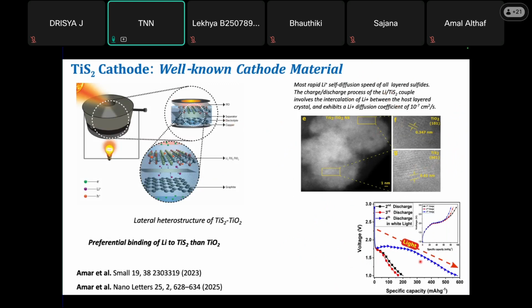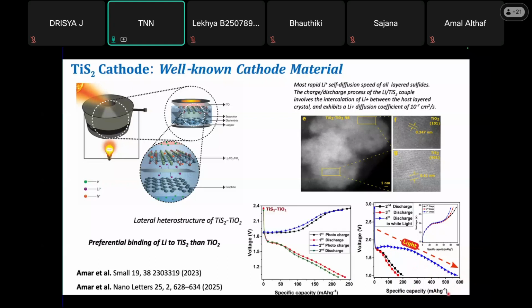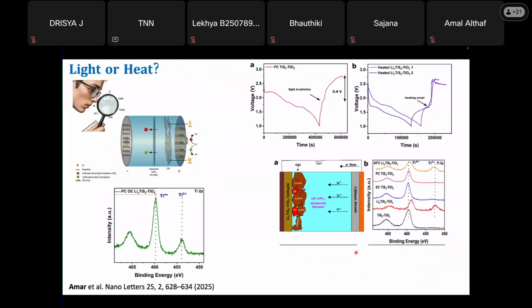Not only that, this can charge the battery back also. While discharging the battery exposed to light, you can actually enhance the capacity. That means you can extend the life of the battery while discharging. So this is also quite nicely possible. We have demonstrated almost 100% charge and discharge capacity, 100% Coulombic efficiency. We also investigated the role of light here. What we found, and I'm just discussing one particular paper in brief, is that if you have the right geometry for photocharging, without the degradation of the solid electrolyte interface, you can actually charge the battery back.